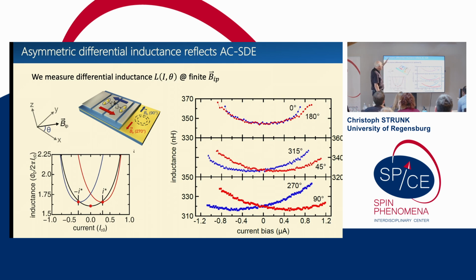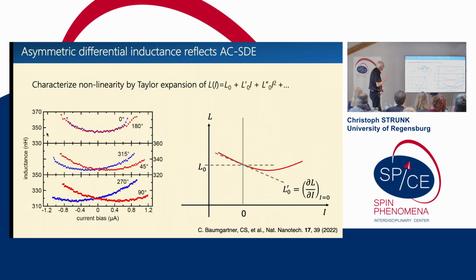But if we now rotate the field so that there is a component perpendicular to the current direction, then these two curves shift against each other, with a maximum shift for 90 degrees. And that means that the cartoonish picture reflects reality.